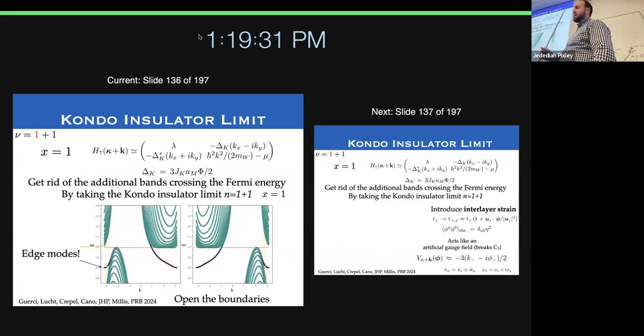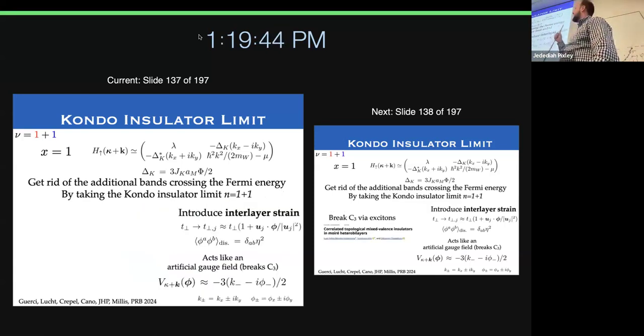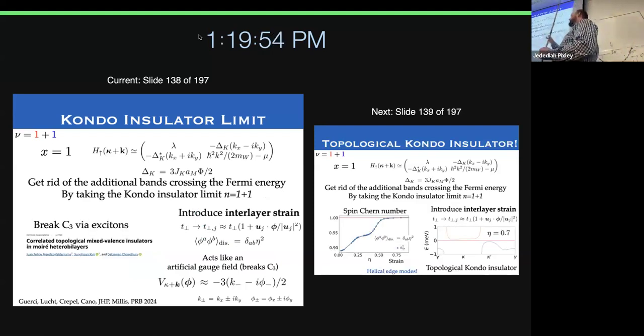But if I open my boundaries, I have edge modes. Okay, so this is an open boundary on the left and right side. These edge modes are signatures that have some sort of topology. If I could gap out the bands, there are a couple of ways to gap them out. One way we did it, we were thinking a lot about interlayer strain. You basically have to break C3 one way or the other. So this is one way we did it, but Debanjan's group also thought about breaking C3 via an excitonic instability. That also might be a natural way to get that. Just want to mention that.